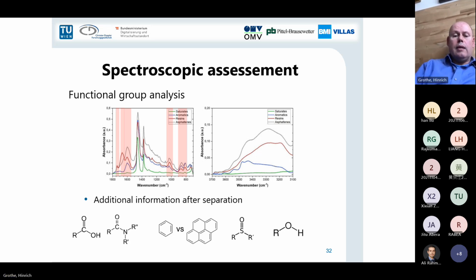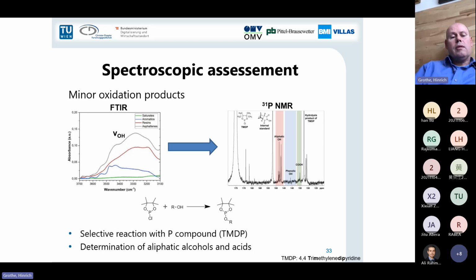And so that's an important thing, because now you can really recognize different functional groups, and you can, for example, also see if you have smaller aromats or larger polyaromatic systems. And you can also see sulfur oxides, and for example, you can also see alcohols or OH functional groups. And this is quite interesting. This is a magnification of the OH stretching mode. And in the infrared, of course, you already see differences. You, for example, can recognize that in a saturate fraction, you see no OH groups, and then you can see the differences between the other fractions. But it's not very detailed information.